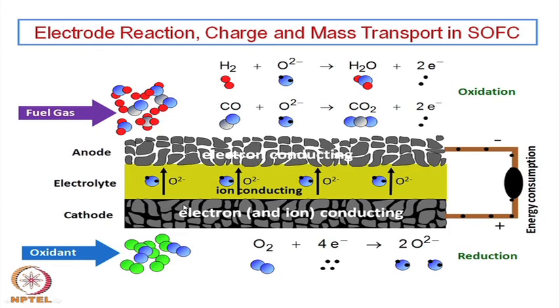So, this is another requirement of the electrolyte, because on one side of the electrolyte there is a very high oxygen potential, a highly oxidizing condition, and on the other side a highly reducing condition, because hydrogen is highly reducing. So, this electrolyte must be thermodynamically stable both at high oxygen potential as well as low oxygen potential. Otherwise, this material will get reduced or oxidized. So, there will be non-stoichiometry setting in, because